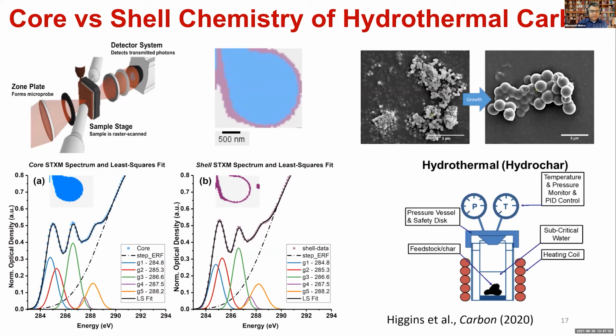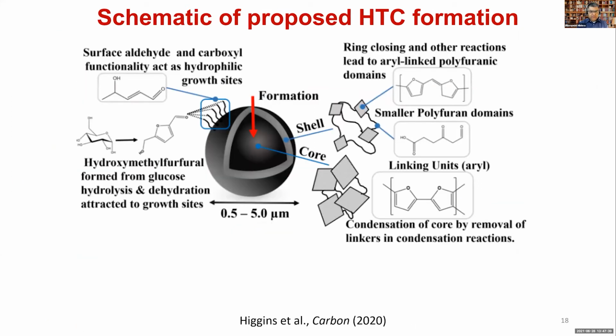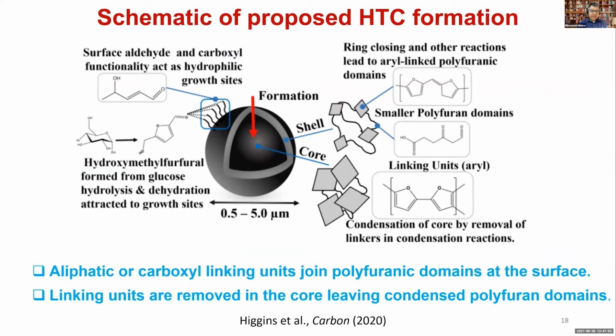So using this, we were able to construct the formation mechanism of HTC, which is something that was missing for a long time. And we concluded that aliphatic or carboxyl linking units join polyfuranic domains at the surface, while the linking units are removed in the core, leaving condensed polyfuranic domains. So this is something again that was really neat work, and it was a technological challenge that this community had never done, or was not aware of things like STXM, and STXM was able to provide really good answers.